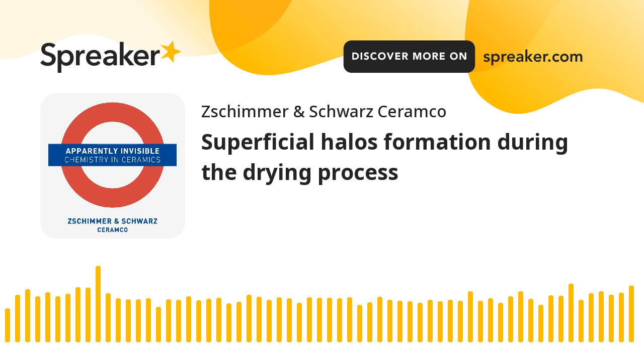But let's step back and take a closer look with an important question. Where do these kinds of anions or cations come from? I don't want to simplify, but three are the most relevant. First, dispersants for ceramic mixtures that are sodium silicate based. Second, the processed water. And third, the inorganic raw materials of the ceramic mixture.